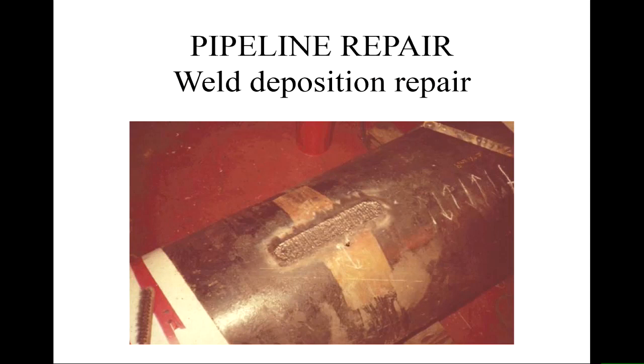Sometimes you might just want to repair your existing pipes by depositing weld metal into the corrosion repair rather than actually filling it with grout. So here is a weld deposition repair. This has been dressed, it's been ground out for corrosion damage, and then somebody has welded this with passes backwards and forwards. Can you see the arrows here? That's somebody saying to the welder, I want you to do this. Weld this way, then this way, then this way, and this is the number of passes you're going to do. Right? And it works.